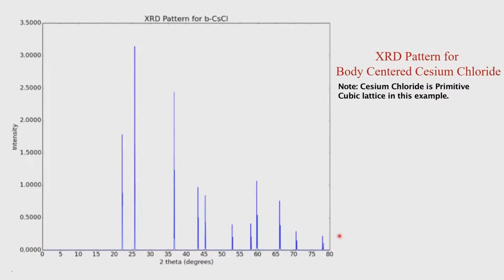The x axis represents the geometry of our diffraction condition, and the y axis represents the intensity associated with the diffraction measurement. So, the corresponding intensities come from the individual calculations which we did for I100, I200 and so on. We calculated those intensities, and they come because cesium is at 0 and chlorine is at half. This discussion therefore assumes that we know the structure.